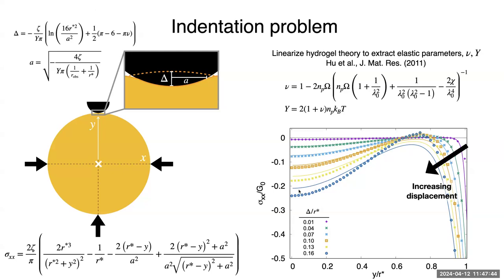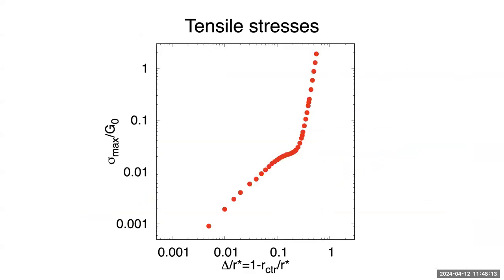We then linearize the hydrogel theory to extract these effective elastic parameters. This is something that we can follow this nice paper for, and we can plot curves, and we see what we would expect, which is as we increase displacement, we see this gap between theory and simulation, increasingly at odds. So what I'm plotting here is the stress in the x direction. So that's this stress here along this middle line. I'm plotting a slice through this point. So that's exactly where we saw the largest tension show up in our simulations, a little bit back from the indenter right around here. So that's this bump right here where we're seeing these positive stresses. That's the tension that we were so interested in understanding. So what I'm going to do is I'm just going to plot the maximum over each of these lines, and we're going to see from the theory prediction how much of this data can we explain. And we get this. So this is a little disappointing, right? We went to all that work, and we're getting just a few data points that we might not have even been able to see if I hadn't plotted this on a log-log scale. So we were hoping maybe linear theory we would get a little bit more mileage out of, but that clearly isn't the case.